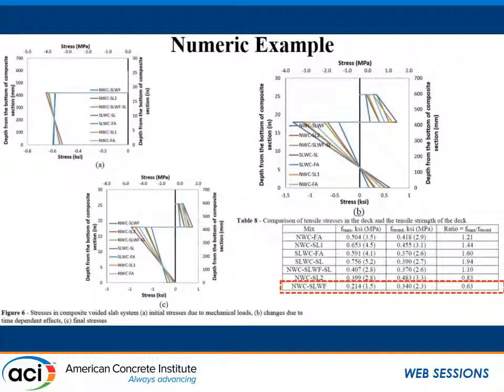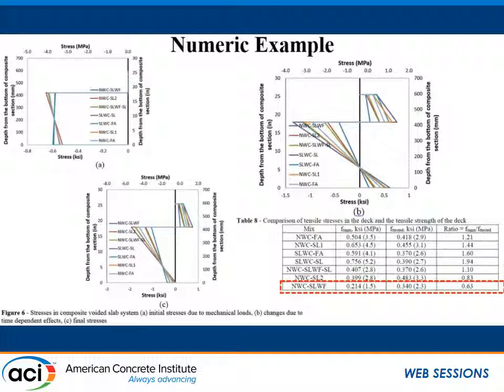Here are the results of the numeric investigation. The first plot shows the initial stresses in the voided slab — including self-weight, the pre-stressing force, and the weight from the cast-in-place topping. The second plot shows the changes in stress over time as a result of differential shrinkage and shrinkage-induced creep. The third plot shows the final stresses in this composite system. The table shows a comparison between the maximum tensile stress at the bottom of the deck and the corresponding tensile strength of each mix. The mix that supplies the lowest ratio is the mix with normal weight coarse aggregates and saturated lightweight fine aggregates, with a ratio of 0.63. There are only two mixes that produce a ratio lower than one, meaning that if the other mixes are used, there is a potential for transverse cracks along both spans of this bridge.